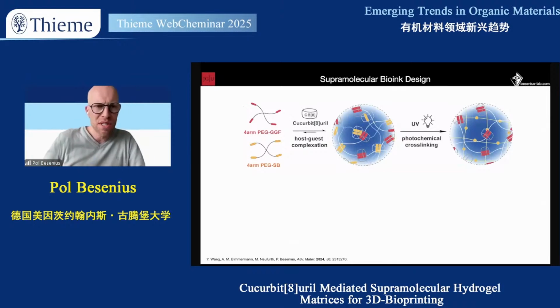We use macromonomers to do so. The chemical entities will be shown on the next slide. It's a polyethylene glycol backbone. It's very hydrophilic, very water soluble, very biocompatible as well. And then you end-functionalize those polyethylene glycol four-arm star PEGs, as they are referred to. They're multifunctional, so every chemical entity leads to a crosslinking site. And this is where CB8 comes into place.